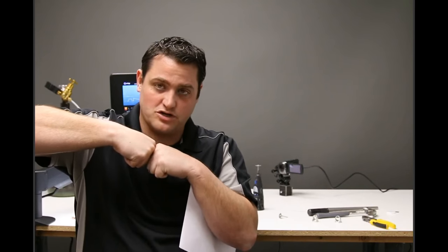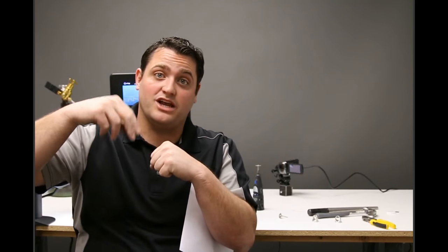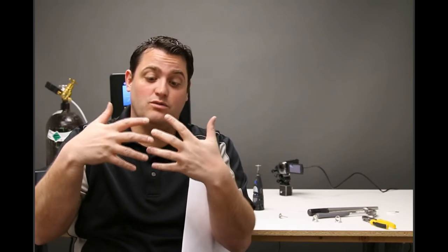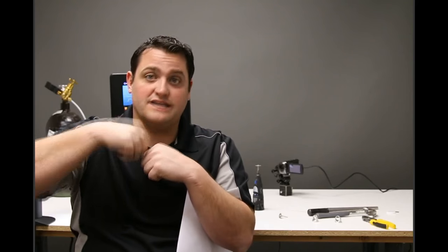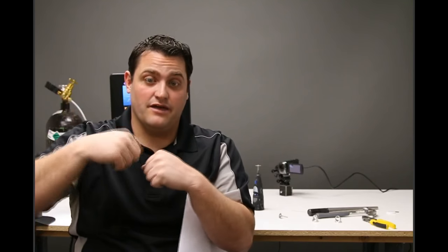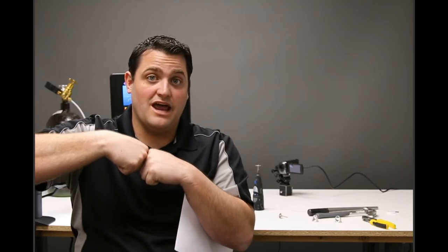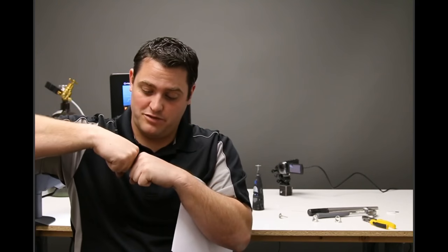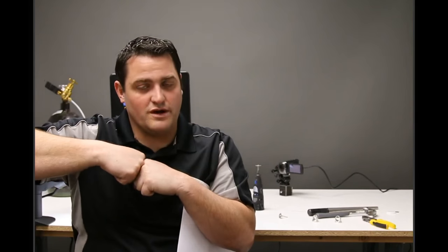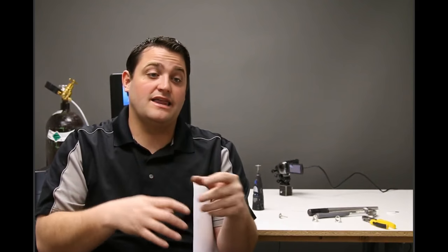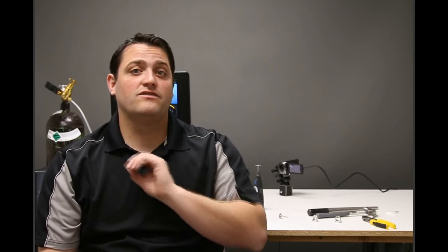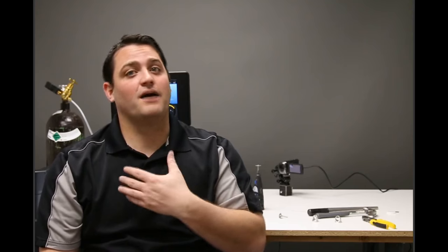And so as we put pressure towards them, we're going to apply energy through it, and where those pieces are touching, it's going to heat up through the resistance. The resistance and the electricity is going to heat up, and then it's going to melt in those specific places and allow them to be joined into one piece. And that's important, specifically stainless steel is really easily welded, but because silver is so highly conductive, the energy flows right through and doesn't create enough heat in that localized area at the energy settings we're used to.